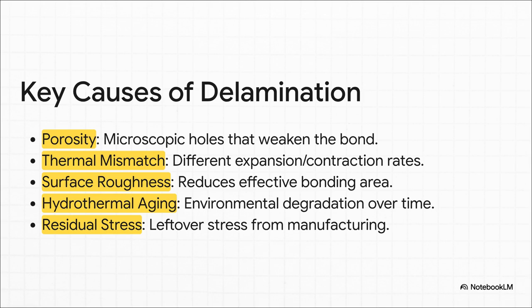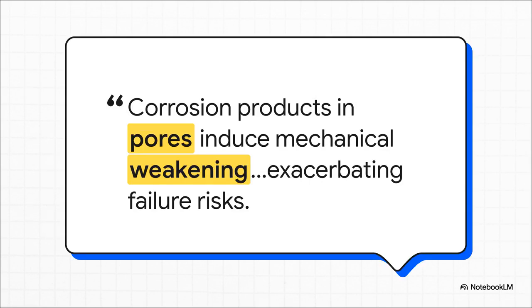And this quote right here really drives the point home. As these researchers explain, those tiny little pores aren't just sitting there. No, they can actually trap corrosive gunk that actively attacks the bond from the inside out, making failure almost inevitable. It's a small flaw with huge consequences.